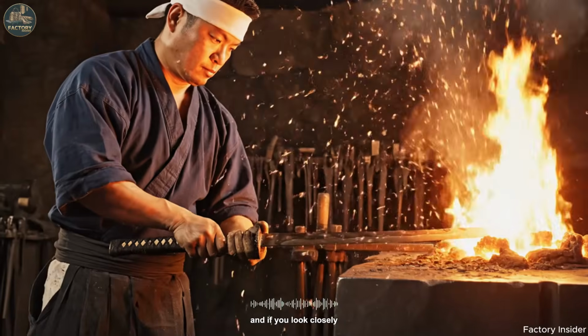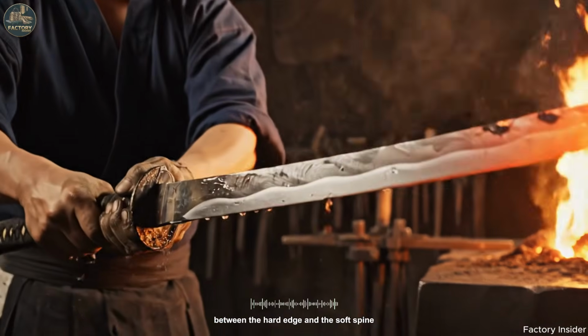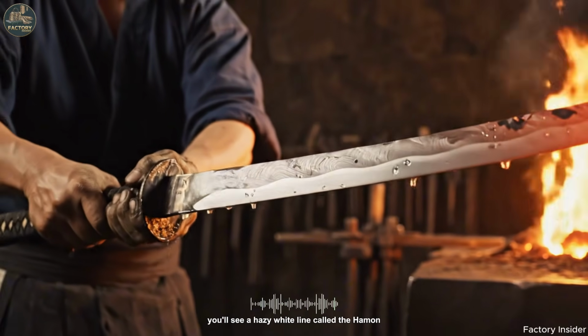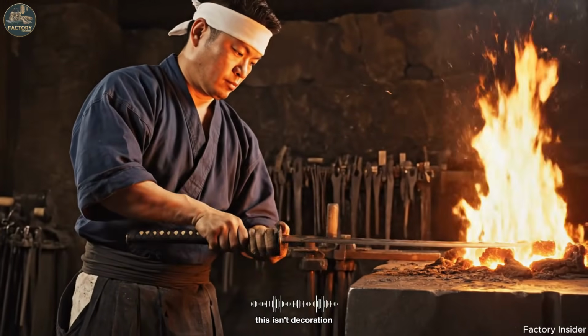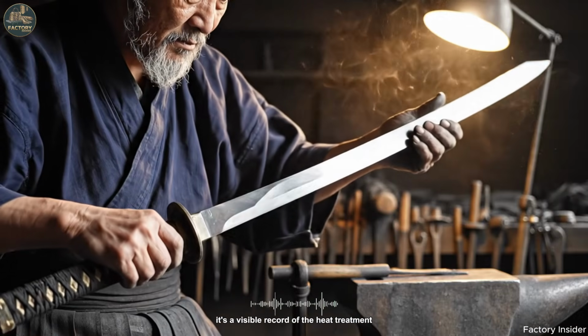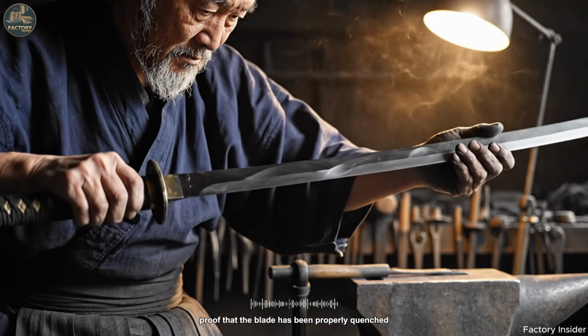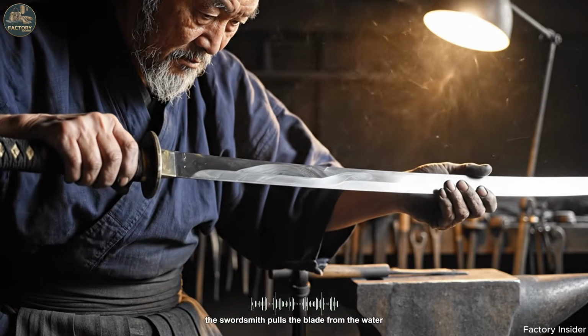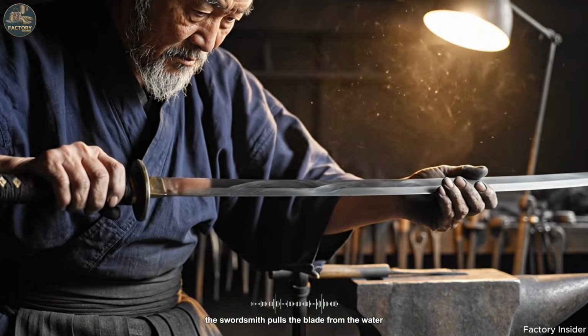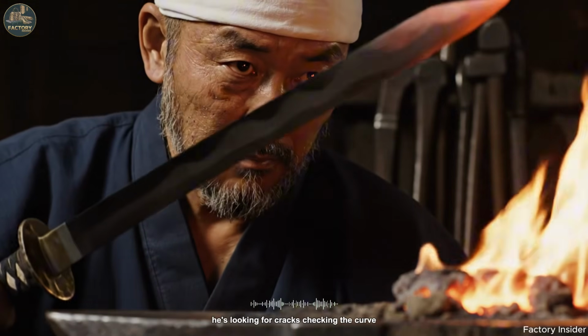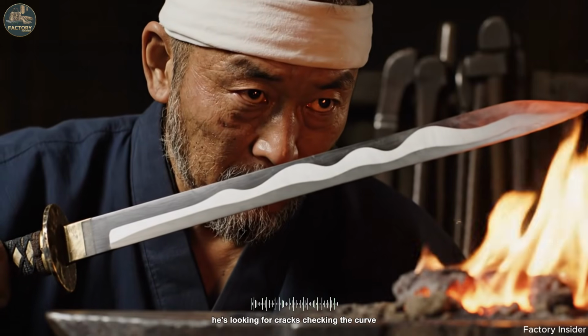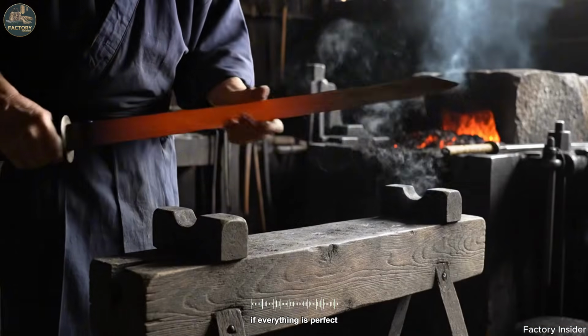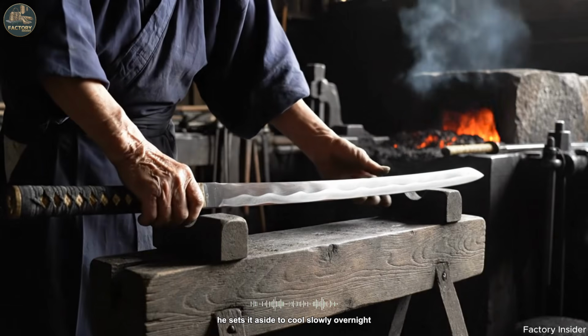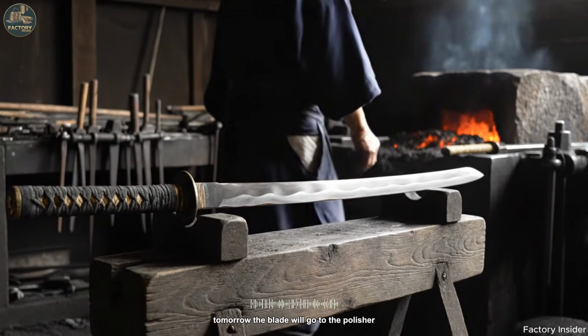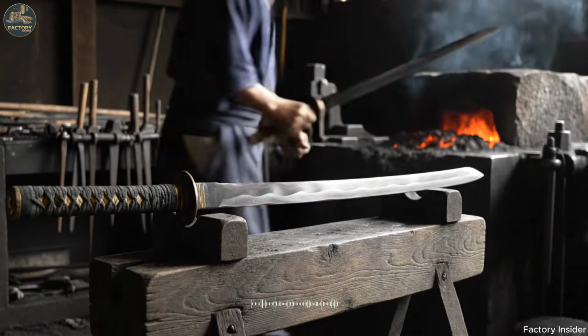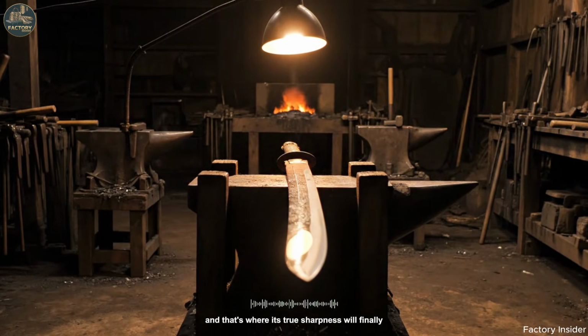And if you look closely at the boundary between the hard edge and the soft spine, you'll see a hazy white line called the hamon. This isn't decoration. It's a visible record of the heat treatment, proof that the blade has been properly quenched and hardened. The swordsmith pulls the blade from the water and examines it in the firelight. He's looking for cracks, checking the curve, studying the hamon pattern. If everything is perfect, he sets it aside to cool slowly overnight. Tomorrow, the blade will go to the polisher, and that's where its true sharpness will finally be revealed.